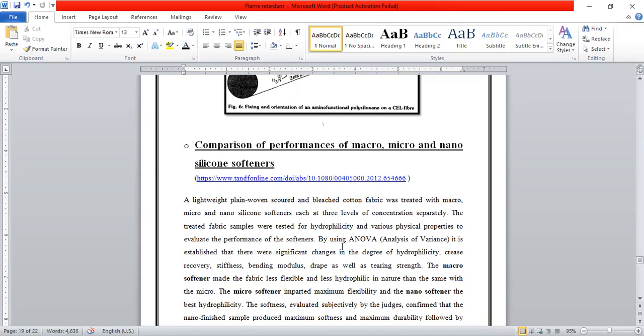By using ANOVA analysis of variance, it is established that there were significant changes in degree of hydrophilicity, crease recovery, stiffness, bending modulus, drape, as well as tearing strength. The macro softener made the fabric less flexible and less hydrophilic in nature. The micro softener imparted maximum flexibility and the nano softener the best hydrophilicity.